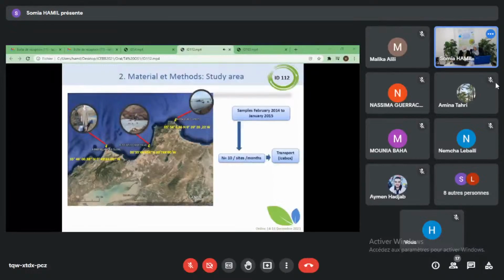The comparative analysis by the post hoc test of metal concentration shows that for copper, the interseed variation is highly significant. However, the interseason variation is not significant between autumn and winter. The interorgans variation is recorded highly significant between female gonads and male gonads, between female gonads and calcareous ring, between female gonads and body walls, and between female gonads and intestine. The intersex variation is recorded as highly significant.